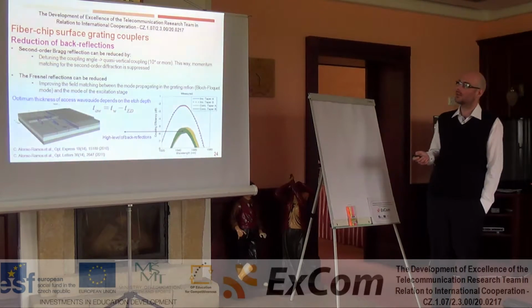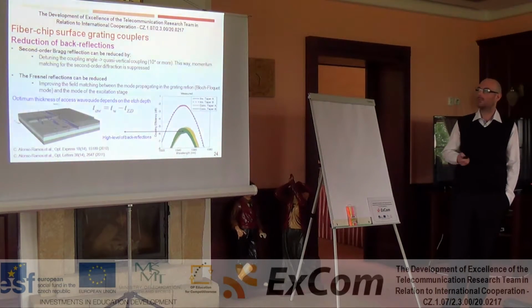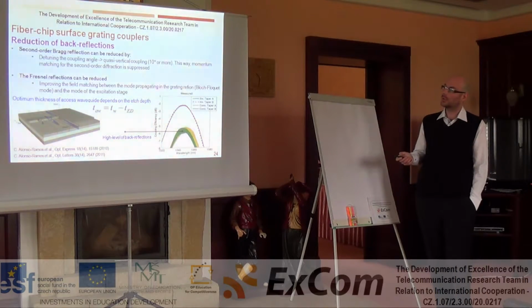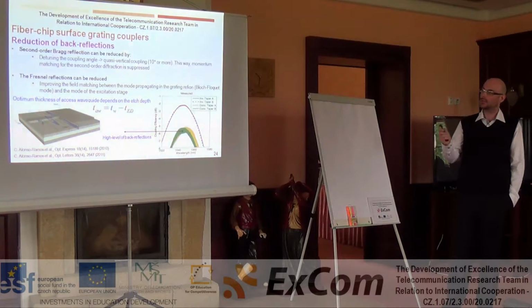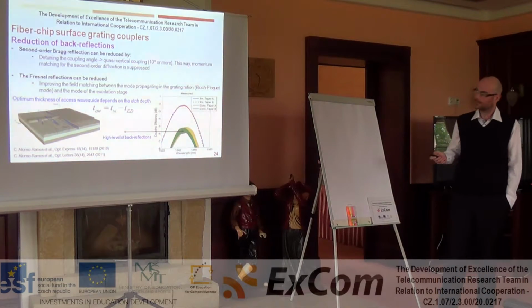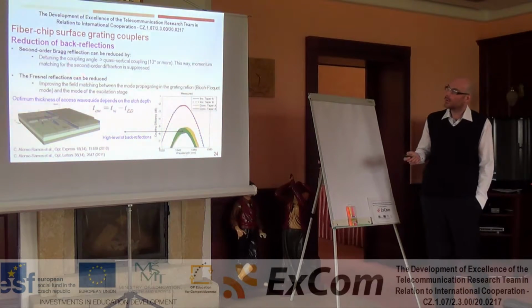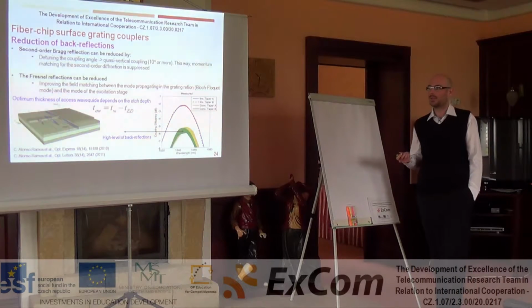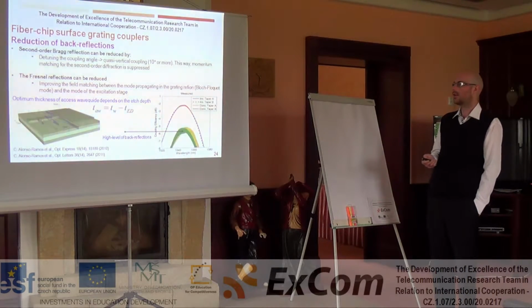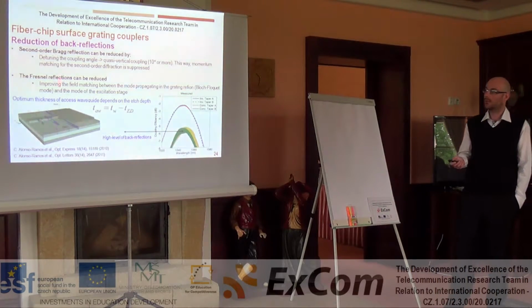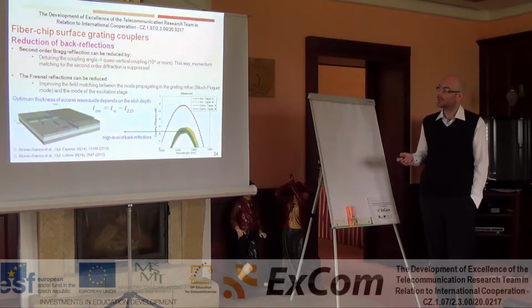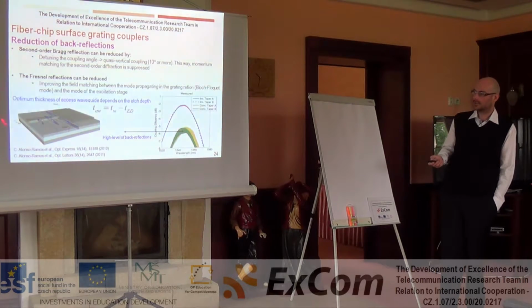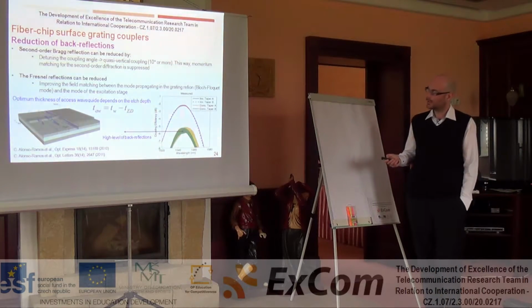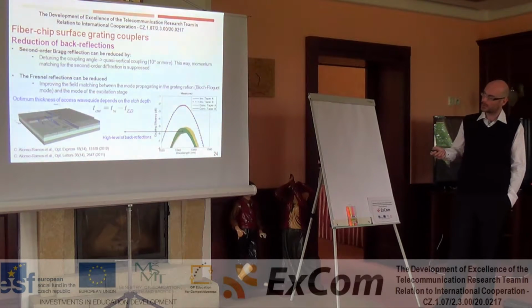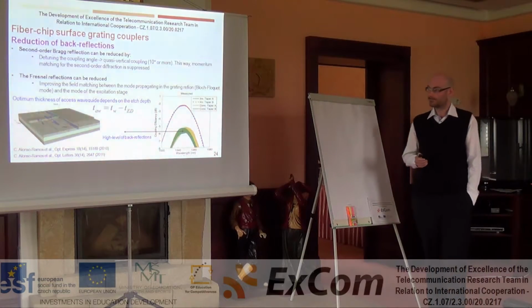So, second order back reflection can be reduced by detuning the coupling angle. In typical grating coupler, we use quasi-vertical coupling. That means that the optical fiber is tilted by some degrees. In this way, momentum matching for the second order diffraction can be suppressed. The more serious issue is the Fresnel reflection. Fresnel reflection can be reduced by improving the field matching between the mode propagating in the grating region here and the excitation stage which is here. In this way, we can significantly reduce back reflection. In grating coupler spectrum, we can see that back reflections are presented here by means of Fabry-Perot ripples.